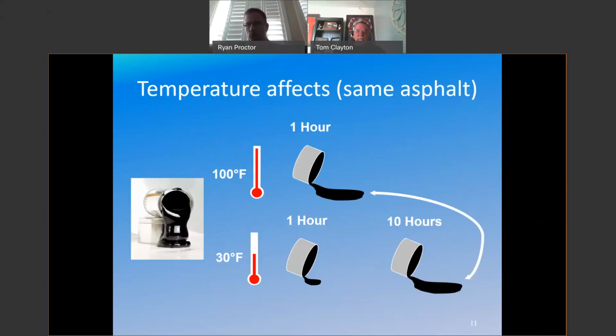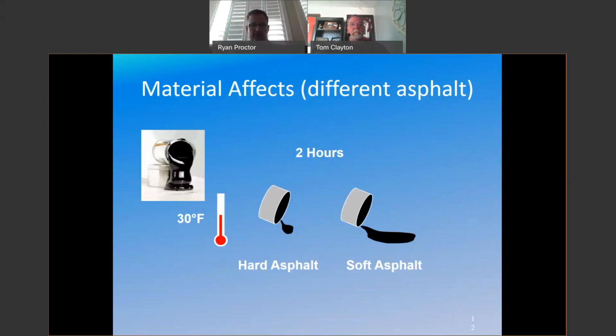So just to kind of hit this home one more time, if you look at that can on the left, if you took asphalt, normal asphalt, I should say, something that wasn't really hard, something you would pave with, and tilted it on its side, eventually that asphalt would creep out of the can and onto the ground. Asphalt has some interesting properties where it's liquid in some cases, it's a viscoelastic material. It's liquid in some cases and it's solid in others. So with this asphalt, if you heat it up to 100 degrees, in an hour, it's going to flow pretty quickly. At 30 degrees, it's going to flow, but it's going to take longer. That's probably fairly intuitive.